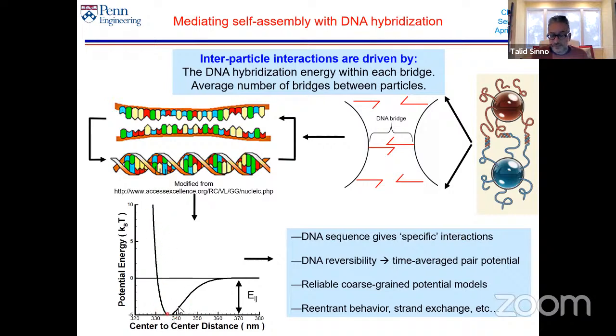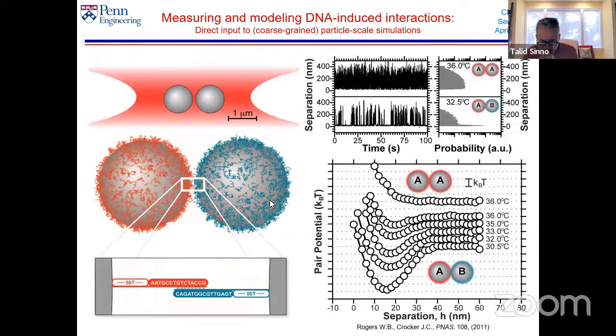It's attractive somewhere in the middle, and then it goes to zero. And this is well understood, especially in the situations I'm going to be telling you about, where the particles are rather large, on the order of a micron, and the DNA strands are rather small, on the order of, let's say, 50, 60 nanometers. So you can think of these as approaching the limits of sticky spheres.